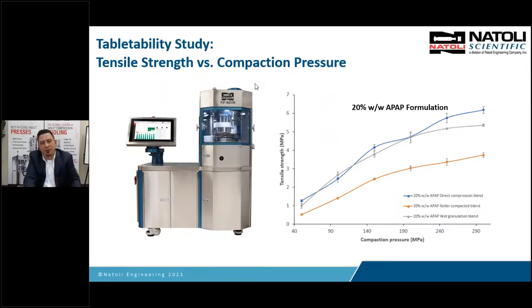This is the workhorse for all of our tabletability studies and strain rate sensitivity. And we want to keep tablet weight constant, and we want to incrementally increase our compaction pressure and collect a sample of tablets at each increment and measure the tablet weight, the thickness, the hardness, breaking force, maybe friability, disintegration, dissolution, and so on. And we enter that into the AIM data acquisition system, and it gives you these profiles.